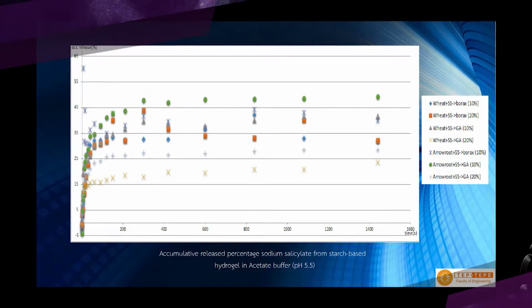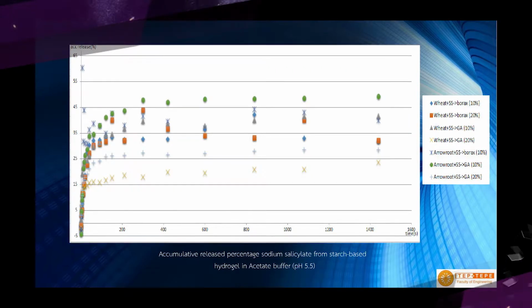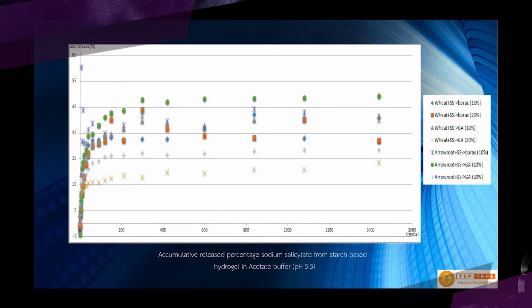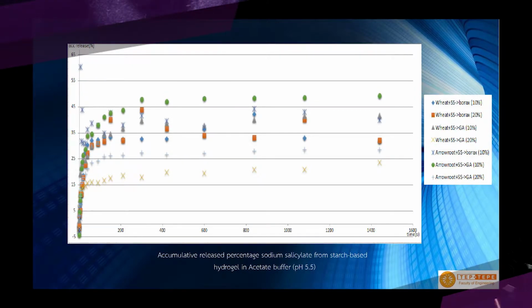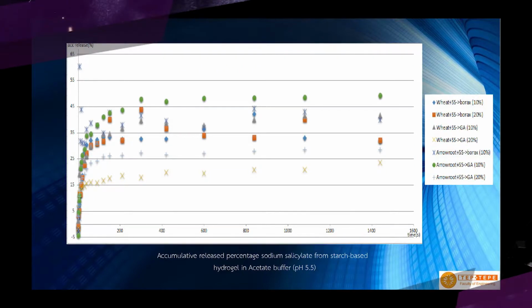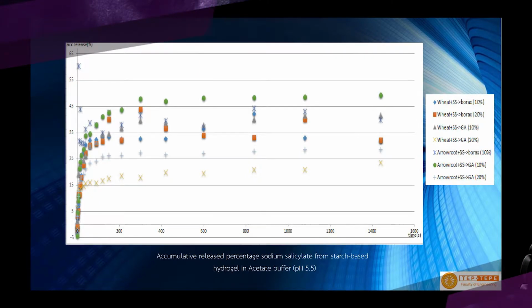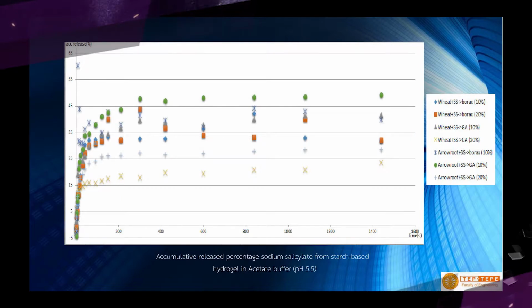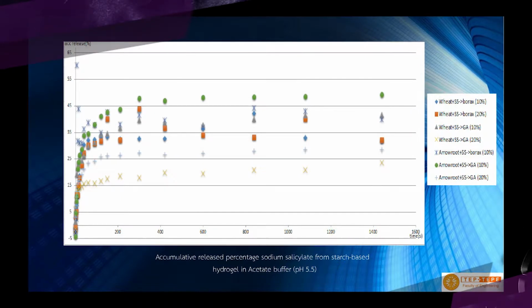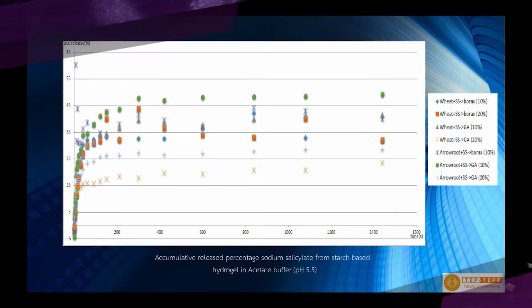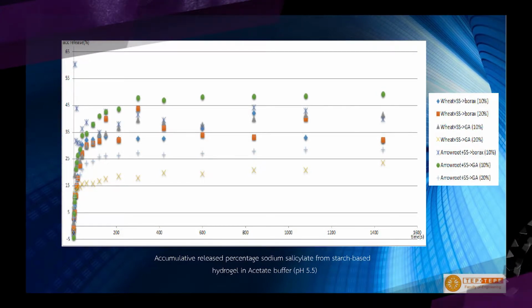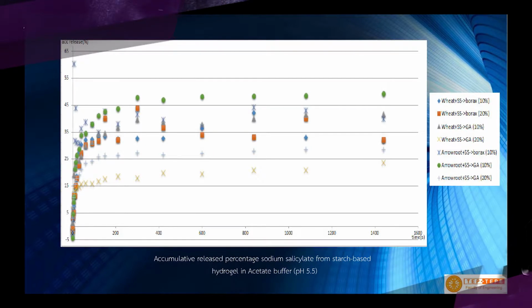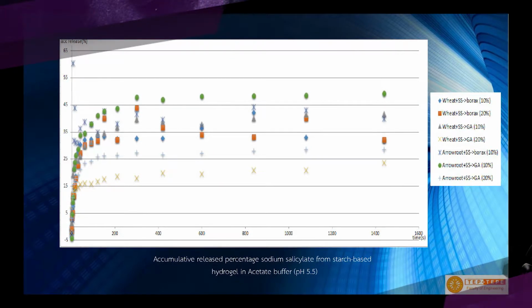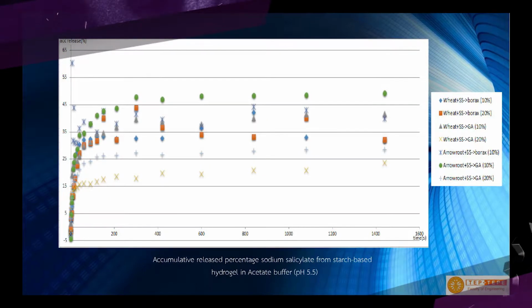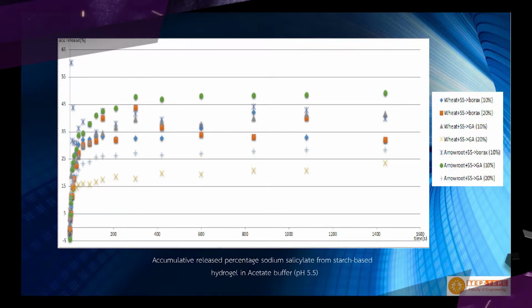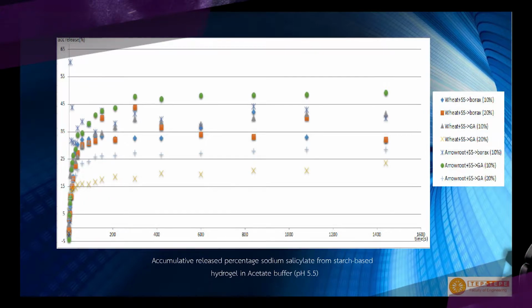This graph shows the accumulated release percentage of sodium salicylate from starch-based hydrogel in acetate buffer at pH 5.5. You can see from the graph that the arrowroot starch mixed with sodium salicylate and 10% glutaraldehyde will give the highest accumulated release percentage of sodium salicylate. The second one is the wheat starch with sodium salicylate mixed with 10% glutaraldehyde. Overall, arrowroot will give the higher accumulated release percentage of sodium salicylate from starch-based hydrogel, and wheat will be second. And the cross-linking agent glutaraldehyde will give a higher accumulated release percentage of sodium salicylate from starch-based hydrogel.